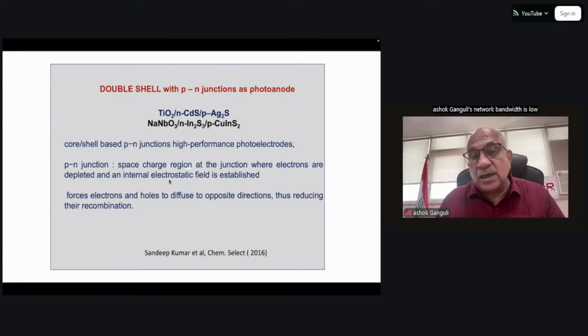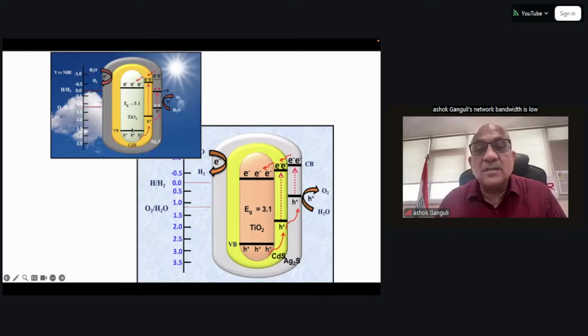You can also do another thing. Instead of having one shell on top of the core, you can have two shells. One is an N-type shell, another is a P-type shell. If you do this kind of geometry of 3 layers, then you can get efficient semiconductor heterostructures. So this is the 3-shell system. So you have initially TiO2, which is a UV catalyst, and then 2 mid-band gap catalysts. One is N-type, one is P-type. And so you know N and P-type create a junction and a charge barrier.